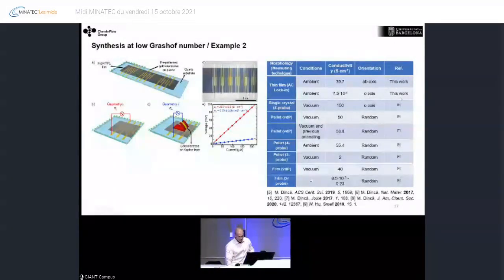This is the previous literature. This is our work, and this is the previous literature. So you see that we measure our films in ambient conditions, so we have the highest conductivity reported. The only one that is also done in ambient is this one here, but there they applied 1 gigapascal to get this conductivity. In our case, we don't apply any pressure. We just take the film that we generated in this simulated microgravity and measure it. We can measure it in all directions.